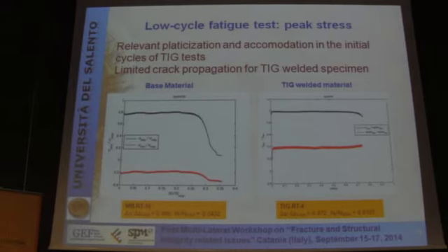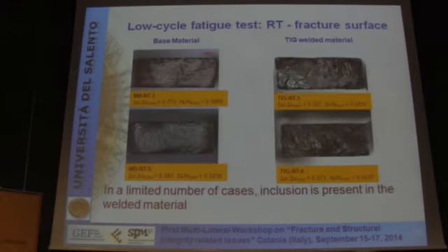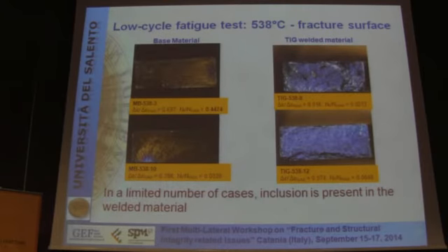And finally, these are the peak stresses that we obtain for a base material or for a welded material. We can observe that the propagation phase is larger in the case of base material, while it is practically absent in the welded material condition. These are the aspects of the fracture surface. In some limited cases, we found some inclusions in welded material, like in this case, but this happens only for few specimens. And this is the fracture surface at the hot temperature.